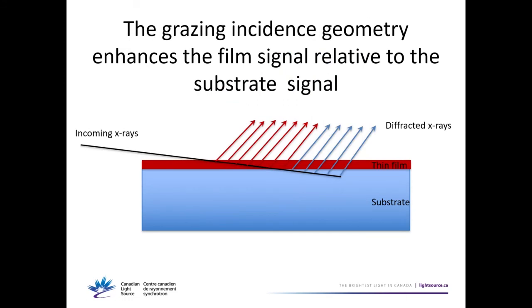To solve this, a common approach is to come in at grazing incidence. When the X-rays impinge the sample at grazing angles, the attenuation length means I have more scattering in the film I'm interested in and less scattering coming from the substrate, which is probably already well-characterized. So we want to come grazing and have most of our X-rays attenuated within the thin film we care about.